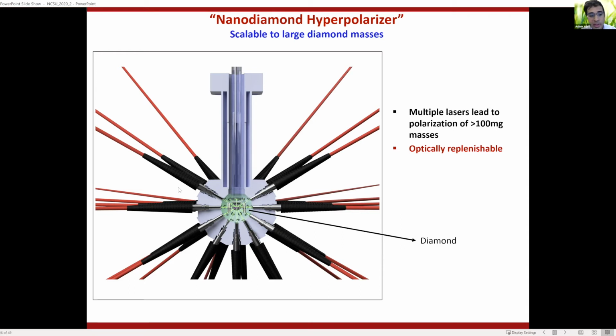So we're actually using 30 lasers all in a dome, and it looks like one of these fusion experiments. The goal here is to polarize a very large diamond mass. We are able to polarize more than 100 milligrams of diamond all at once by applying 30 lasers all at once on the sample, and then actively cooling it and whatnot.